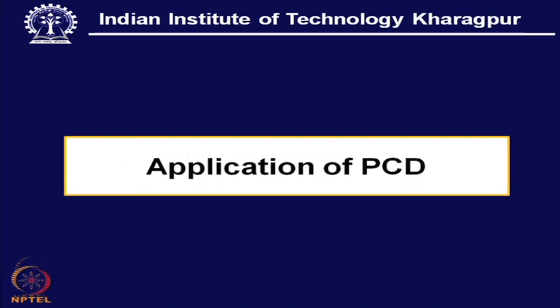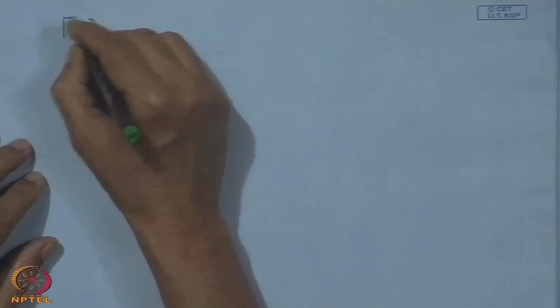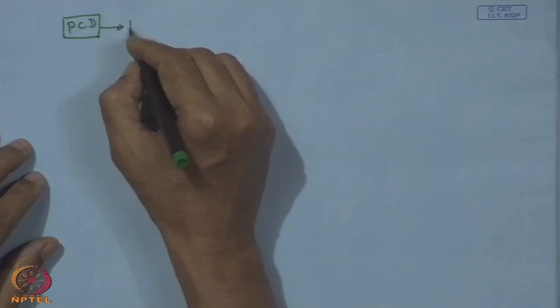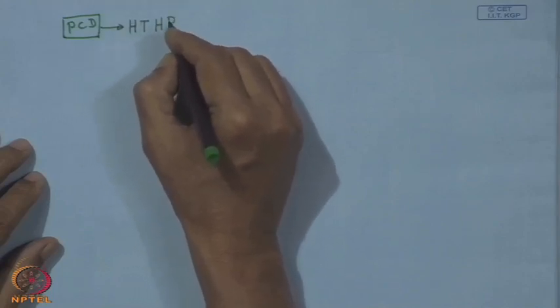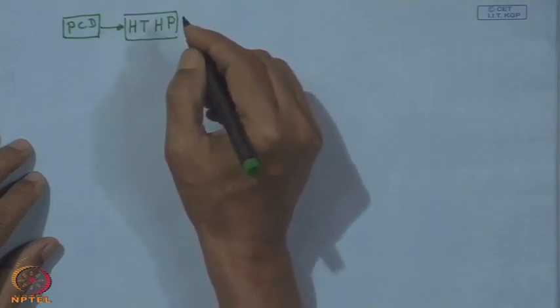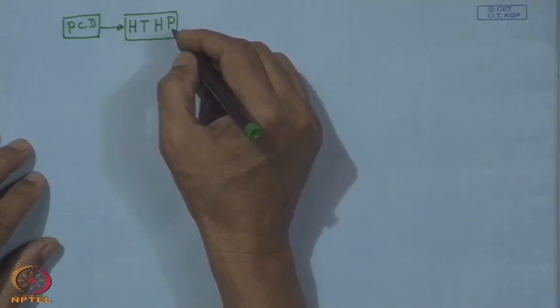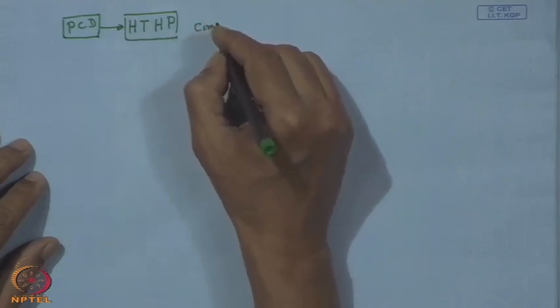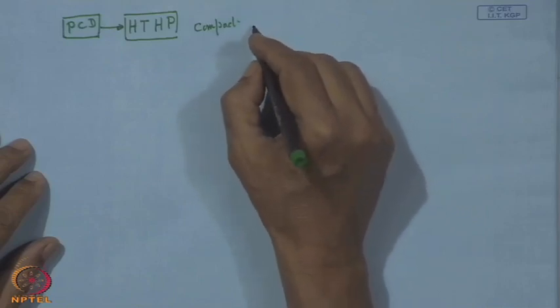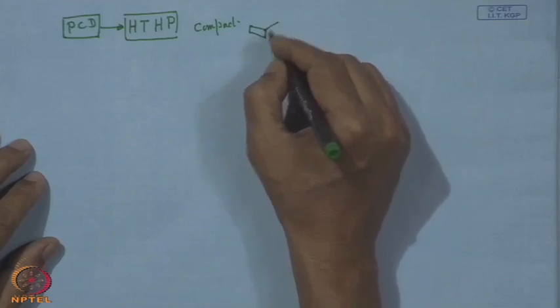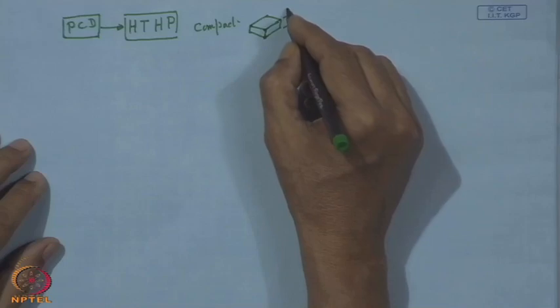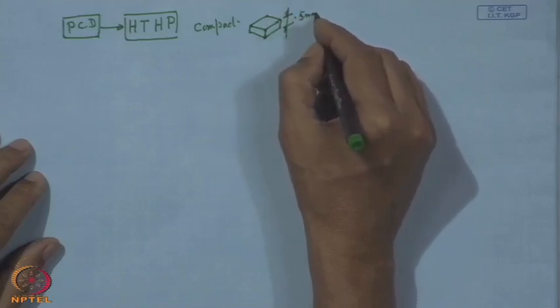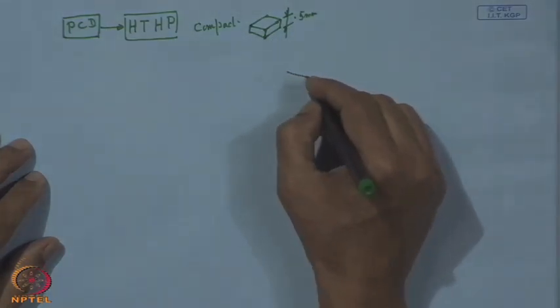Now, as a substitute for this natural diamond, later on the polycrystalline diamond compact came into being. This polycrystalline diamond compact is actually the result of high temperature, high pressure technology. That means, tiny particles of diamond are subjected to high pressure and high temperature to make a compact. And this compact can be in the form of a round bar, or it can have a square shape, and this square shape may be around 0.5 millimeter thick, and that can be brazed on a carbide base.